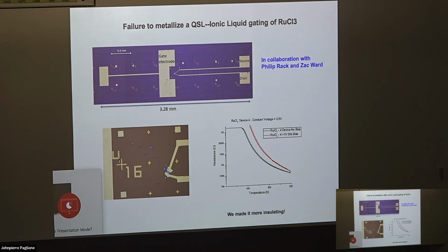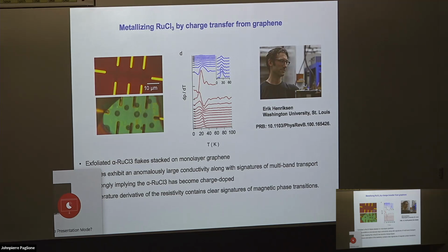And so we tried to do something similar with ruthenium trichloride. We tried to make a device with ionic liquid gating, and it just failed miserably. We actually made it more insulating rather than conducting. However, this actually led to something interesting eventually. So this is Erik Henriksen, who's at Washington University in St. Louis. What Eric did was he wanted to monitor the magnetic transition in ruthenium trichloride by putting a piece of graphene on top of the ruthenium trichloride and then measuring the transport of the graphene, to see how the magnetic transition in ruthenium trichloride showed up in graphene transport.